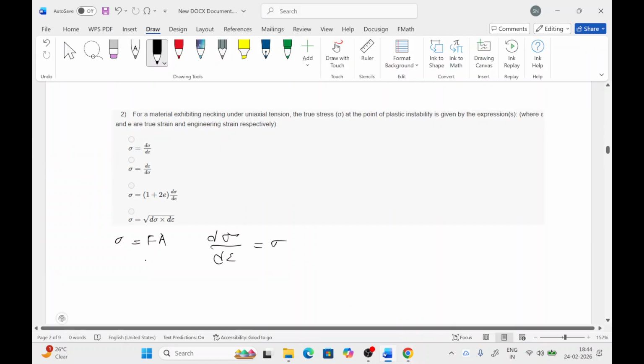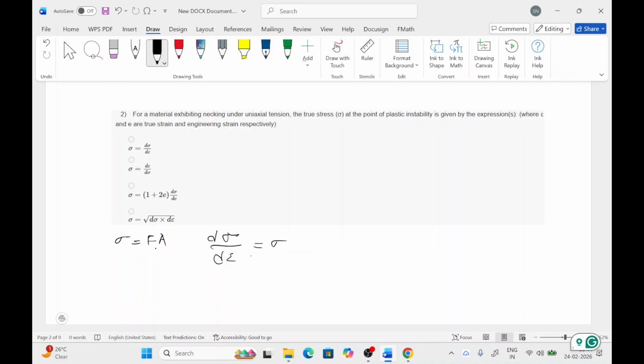Yeah, so for the instability, we got this term by differentiation of this term, sigma equals f a. So the plastic instability equation is given by this formula: d sigma by d epsilon equals sigma. This is the sigma epsilon curve, and the d sigma by d epsilon curve is the strain hardening rate.